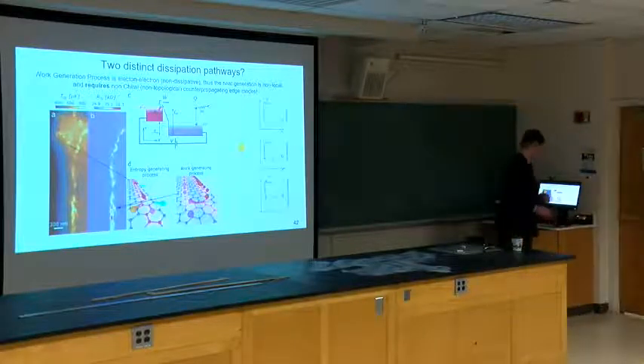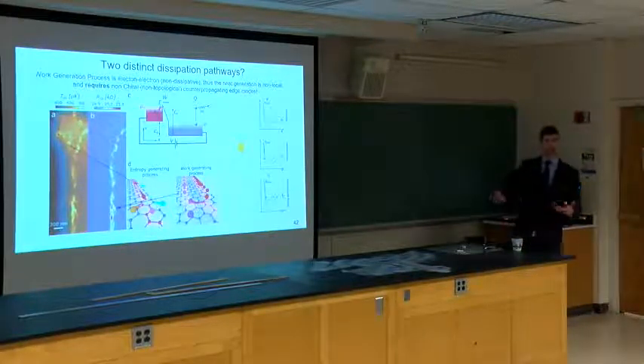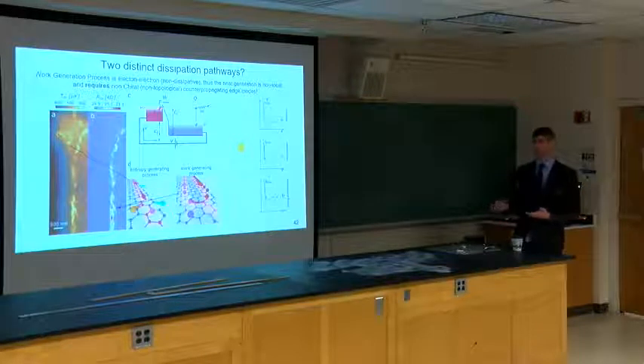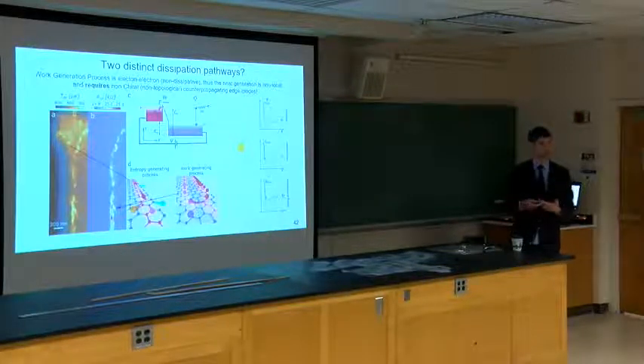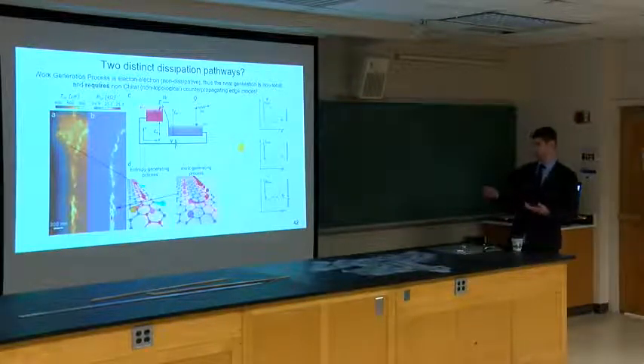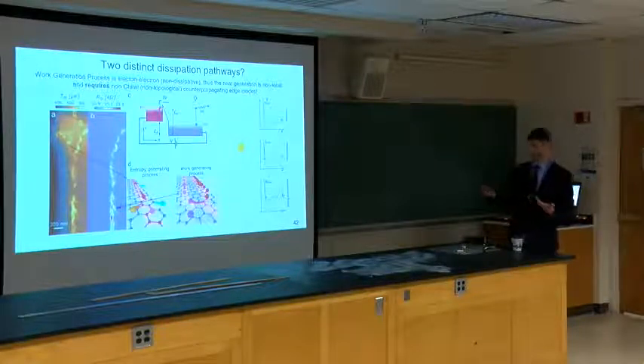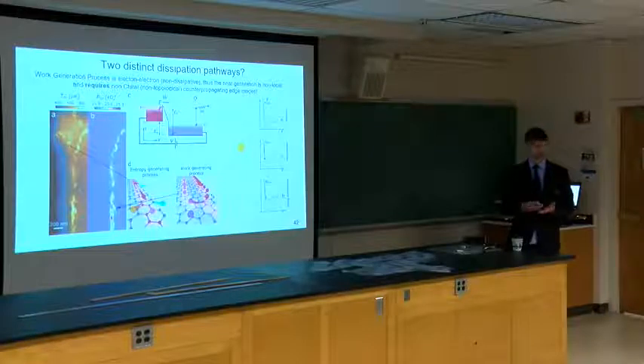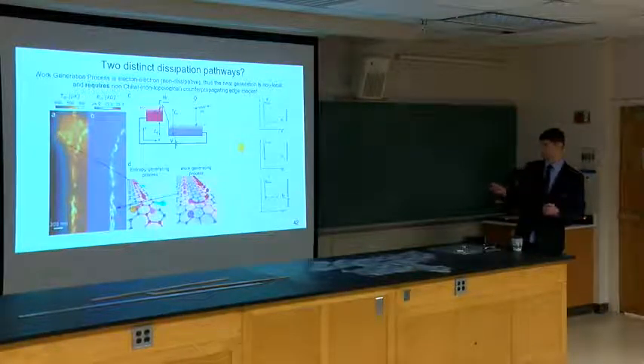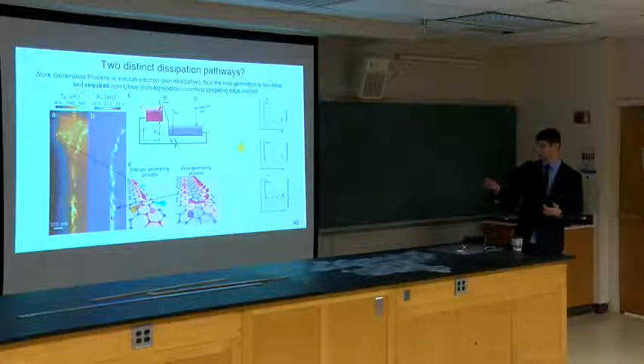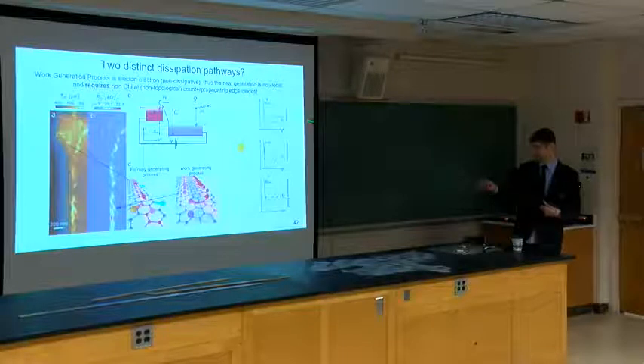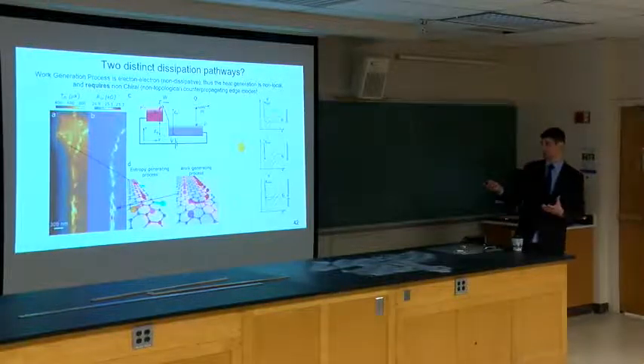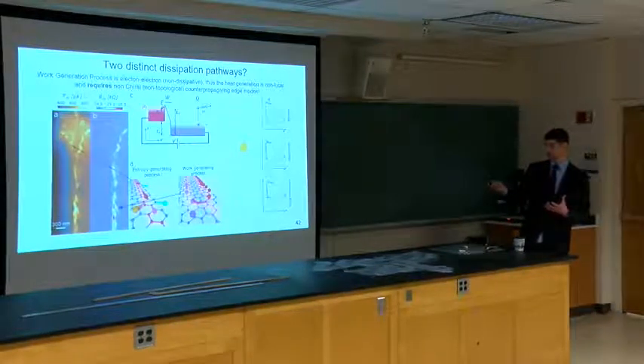The thing that this requires, however, is that quantum Hall edge states are non-chiral. So we need a counterpropagating edge mode to exist in order for this to happen, and that's a bit odd in that we didn't really expect this in graphene. You see it in 2 DEGs sometimes, like in the previous constant energy diagram that I showed before, where it was just kind of rounded, and then the bulk of a device would have a flat spectrum.